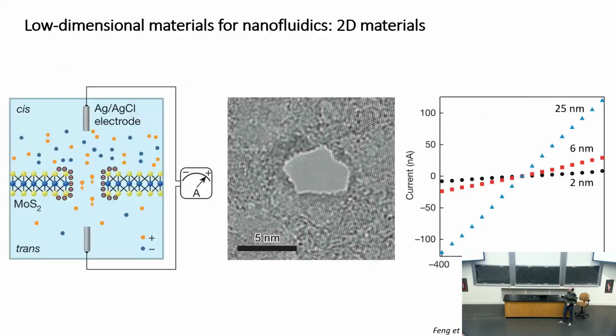More physics-y maybe is doing this on single defects. Here I'm showing an example of an MoS2 pore. It's a single pore in a membrane. What people did here is apply biases across this pore. If the pore is big, you see sort of ohmic behavior in the current versus voltage characteristic. When the pore gets smaller, essentially your current just drops.